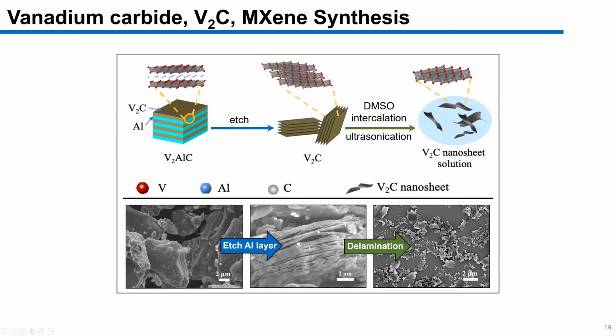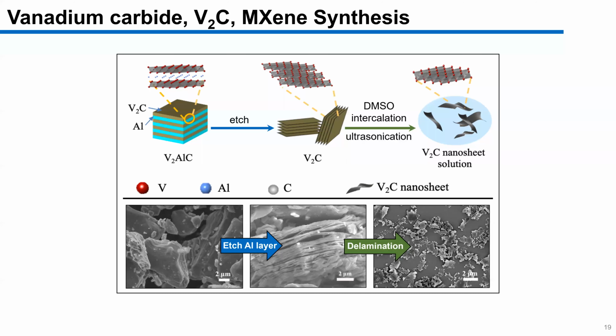We don't have a lot of the equipment needed to do that. There's a sintering process that occurs where you are able to promote binding of vanadium and carbide or titanium and carbide with the aluminum interlayers. So that process we don't do right now, at least in our lab. If we functionalize the material in some way, we would have to start from generating the MAX phase to begin with, but that's in the future for us.